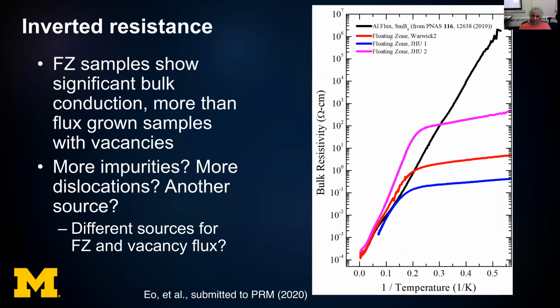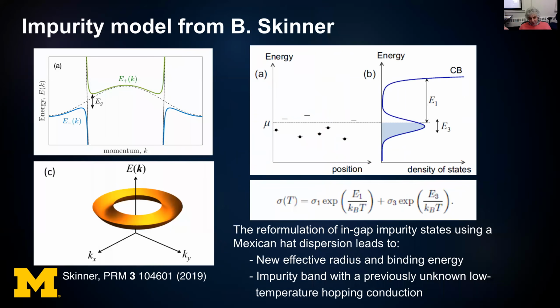And when you put the data together, you get more questions than answers, but roughly speaking, there is no question the floating zone samples always have more bulk conductivity. Sometimes it's so dominant that you can't see the surface conduction. And the behavior is not the same as the ones that I've shown earlier, where there was a flat plateau. And the goal, of course, of our study is to get to the bottom of it, to see exactly which disorder contributes to conduction. There are actually 2 candidates, and they might both be present.